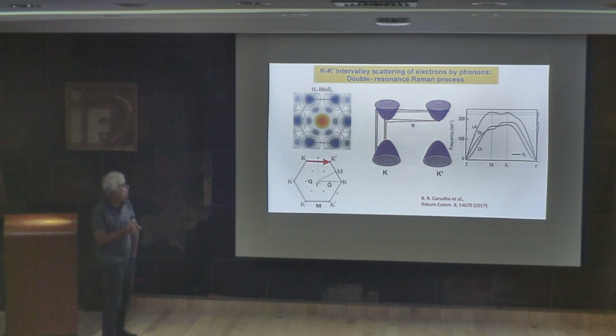For example, in the case of one layer of molybdenum disulfide, we have one valley near the K point, another valley near the K prime point. The dispersion is different from graphene, that's linear. In this case, we have a gap, a semiconductor, but we also have the same kind of process that appears when we are in resonance, showing that we also have peaks that come from the transition of one valley to the other valley.